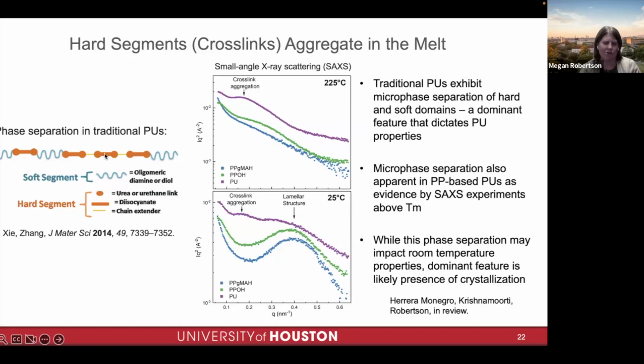And you can see this through X-ray scattering. So we wanted to know in our material, will this happen? And so we looked at small angle X-ray scattering. We looked at a high temperature above the melting point of our polymer. And indeed, we do see a peak here, which we attribute to the aggregation of the crosslinks in our material. If we cool this down, that peak actually persists, but we see the formation of another peak, which is related to the crystallization of the polymer.